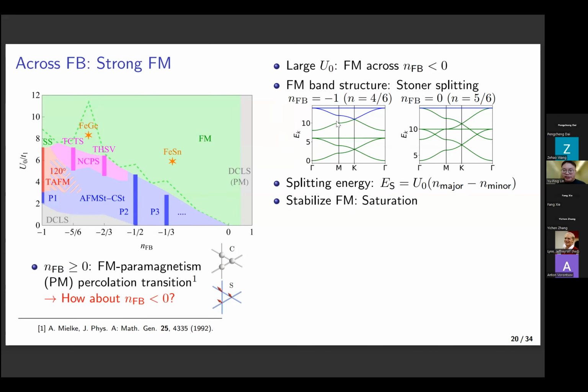And we know that if we want to stabilize the ferromagnetism, we may want to saturate the ferromagnetism such that we're pushing the spin majority bands low enough and we're fully occupying the majority spin. The reason is that if we have the Fermi level of the majority spin above the Fermi level of the minority spin, some of the flatband electron filling might just percolate into the dispersive bands of the minority spin bands, so that we're destabilizing the ferromagnetism. So we want to saturate the ferromagnetism to make it stable.